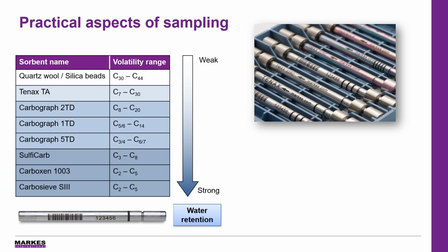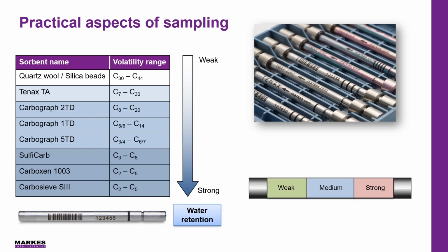And we're able to do this as all Markes TD instruments operate in backflush mode. So just to give you an example of this, if we have our multi-bed sorbent, as you can see in the bottom right-hand corner of this slide, the sample goes on in one direction and then the desorption goes off in the opposite direction. And this is really important because our semi-volatile organic compounds now only interact with our weak sorbents at the front end of the tube and don't interact with our strong sorbents at the back end.